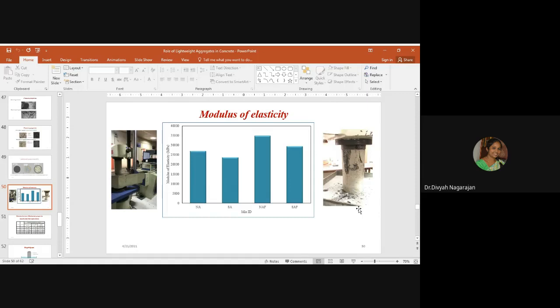Now coming to the modulus of elasticity. As I said, the modulus of elasticity of the fly ash aggregate concrete is generally less than the normal aggregate concrete having equivalent strength, irrespective of the production process. This may be due to the higher cement paste content in the concrete and lower stiffness of the aggregate. It is also observed that the peak stress and elastic modulus of the concrete decrease as the volume of lightweight concrete increases within the matrix.